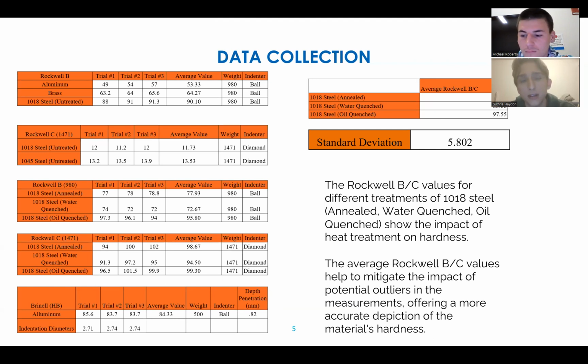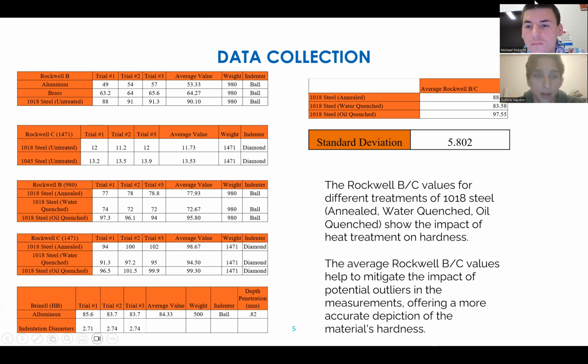As you see on the right side of each column, we have the weight and then the indenter. This is just to further explain the difference between the Rockwell B and C hardness tests. Rockwell B has slightly less weight, only 980, compared to a 1471 weight for Rockwell C. And the indenter is slightly different as well. We have the ball on Rockwell B and then the diamond on Rockwell C. This is just to establish a little bit more of a variance in terms of how we can test our different substances.